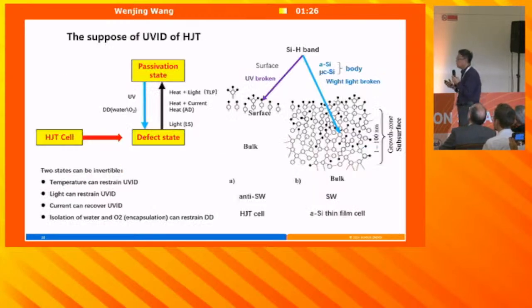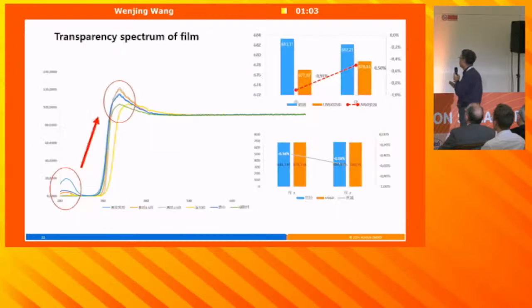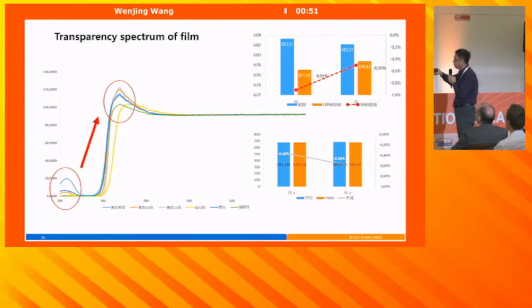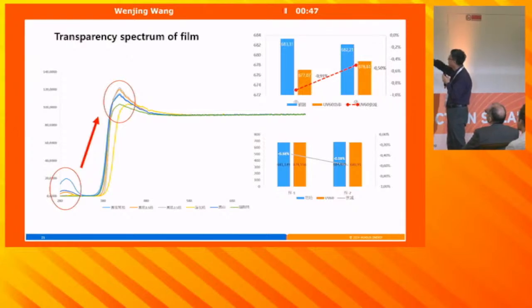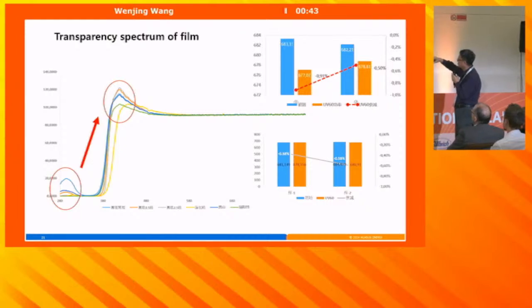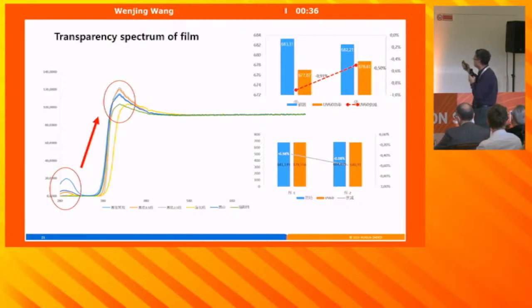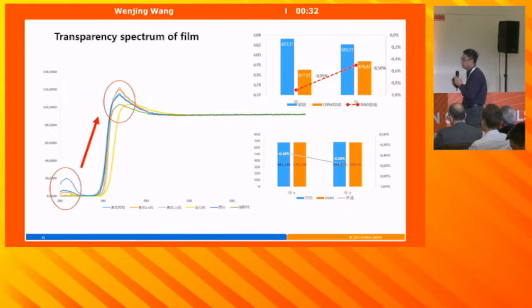So the main reason may be that the UV energy can break down the silicon-hydrogen bonds, making more dangling bonds and causing minority carrier recombination. So we use a special design of down-conversion material put into the EVA or EVE to convert the UV to blue light. If we cut down enough of the UV light, the UV degradation will not be observed at all.